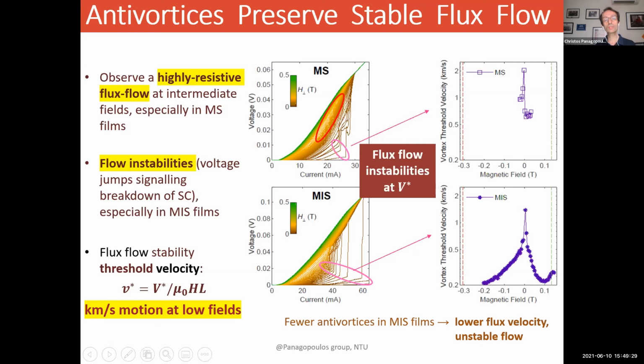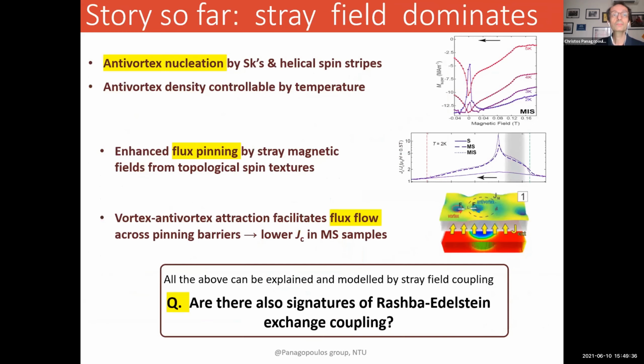And there is a flux flow stability where the threshold velocity, as I mentioned earlier, is kilometers per second at low fields. So the story so far is that stray field dominates in our heterostructures. In other words, there is anti-vortex nucleation in your superconductor by having skyrmions and helical spin stripes above it through the multilayer. And the anti-vortex density in your superconductor can be controlled also with temperature, which I didn't have time to mention, but also with magnetic field.